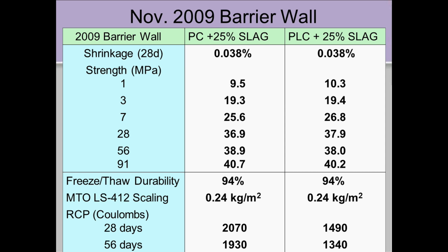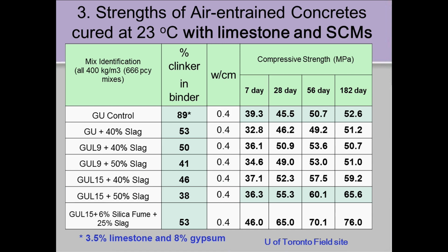The shrinkage is no different. Freeze-thaw durability is no different. The de-icer scaling test we did was no different. And the Coulomb values, in terms of permeability, show slightly better here, but I would say they're not different because of other tests that we've done as well. So without changing anything, they've got 10% less CO2 through more clinker reduction.